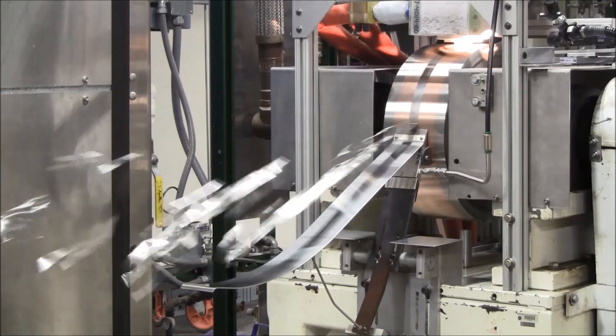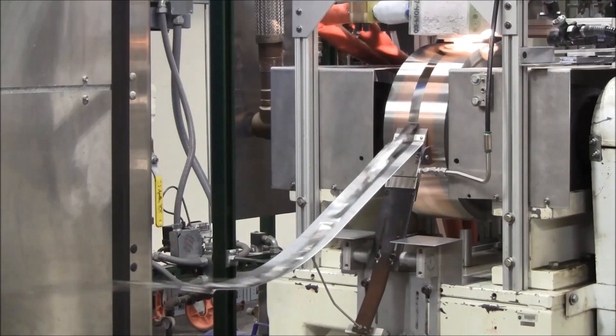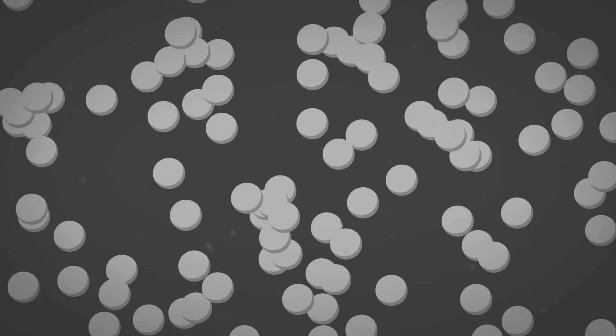We make them that way by casting metal and cooling it at a very, very rapid rate — about a million degrees per second. At that rate of cooling, atoms don't have time to find positions in a crystalline lattice, and so the material remains amorphous or glassy.